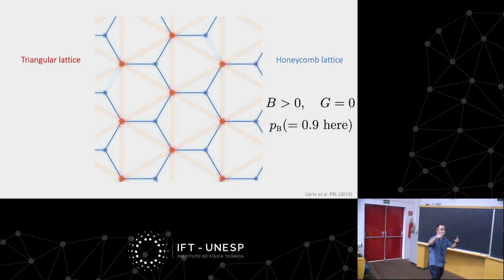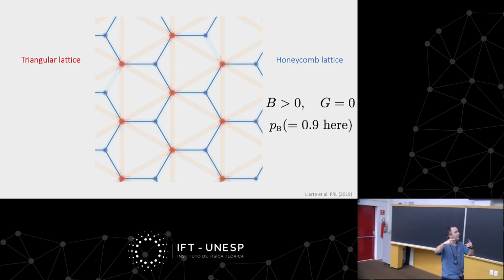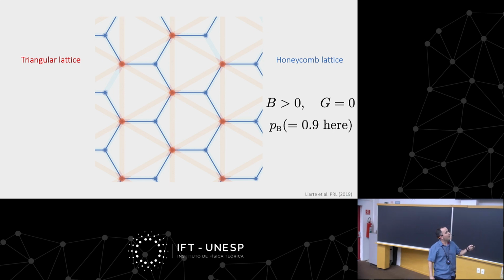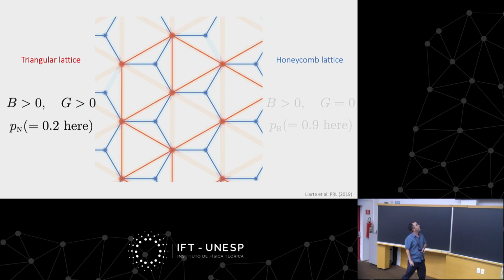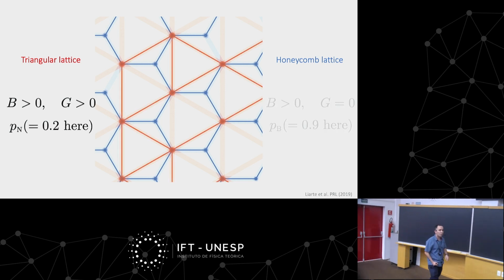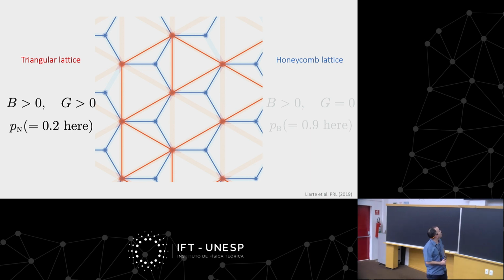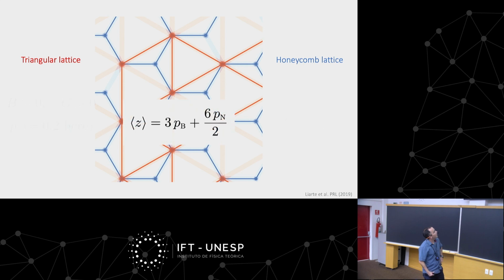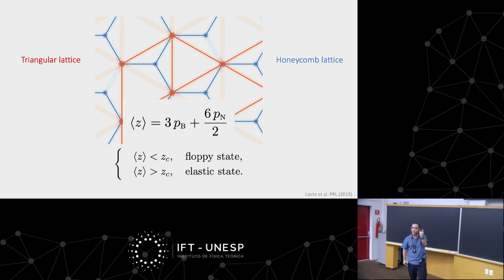The honeycomb lattice has a finite bulk modulus, has a B greater than 0, and a 0 shear modulus. And what I'm going to do, I'm going to populate each bond with a spring with some probability, PB here, which for this figure is just 0.9. And the triangular lattice has finite bulk and shear moduli. And I'm populating each bond with a probability Pn here. Now it's very easy to calculate, for instance, the average coordination number for this combined disordered lattice, and that's just given by this formula. And what you get here is that if this average coordination number is smaller than a critical value, a critical coordination number, ZC here, you have a floppy state.